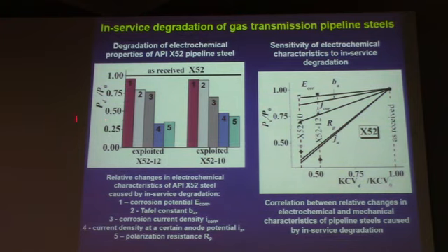And for the results presented here, a ratio of a certain characteristic for degraded material to the same characteristic of the as-received state was used. And it can be seen that relative changes in corrosion potential and Tafel constant were insignificant. However, other characteristics were sensitive enough to material degradation. And determination of the polarization resistance is easier than other characteristics, so we used this parameter for further investigations.